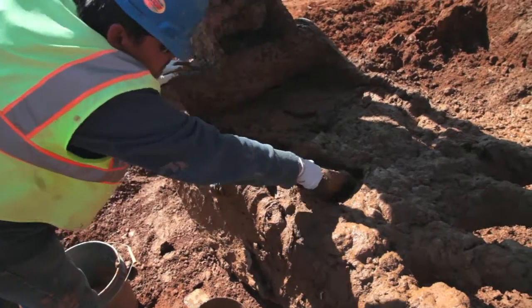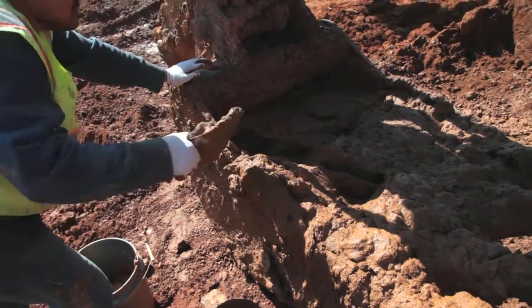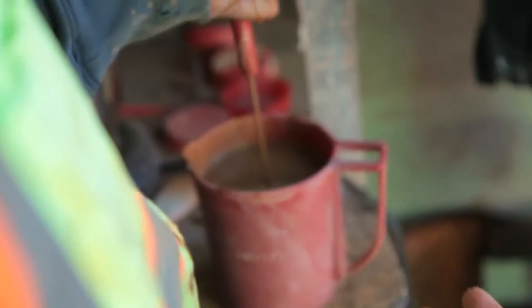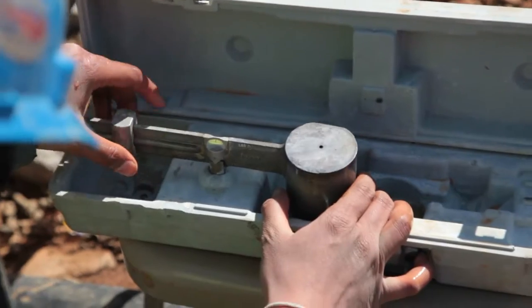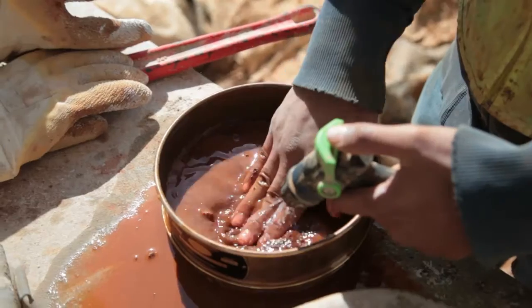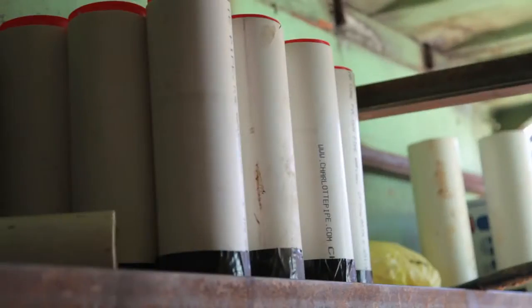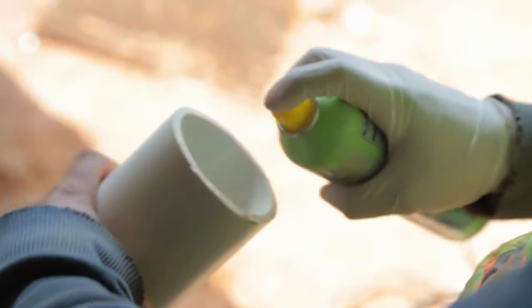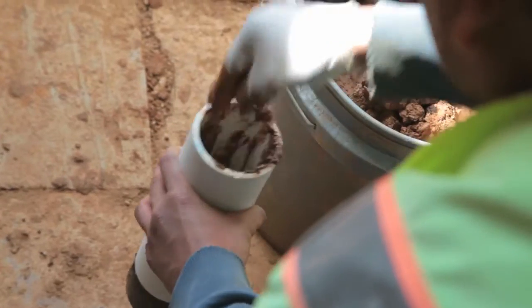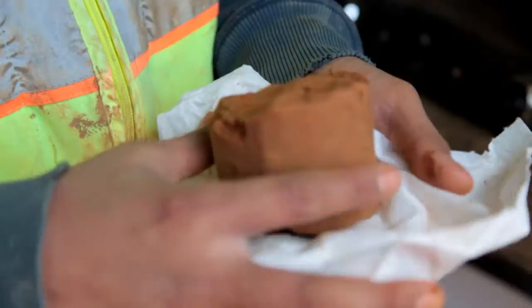The bentonite slurry is tested twice per day. The samples are tested for viscosity by marsh funnel, density by mud balance, and also sand content. Samples of the soil cement bentonite are placed in 3-inch diameter molds for testing in the laboratory for hydraulic conductivity and unconfined compressive strength.